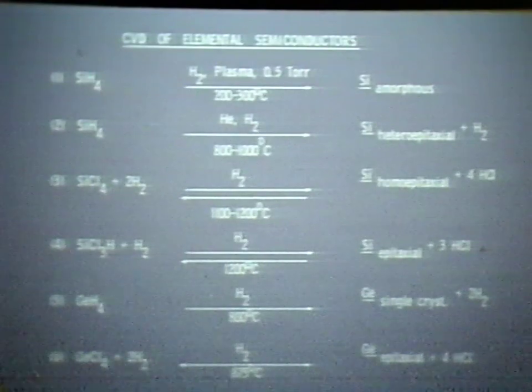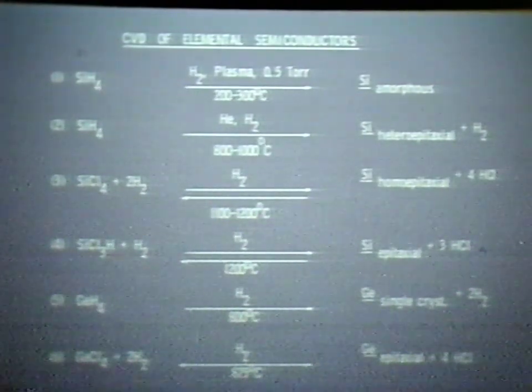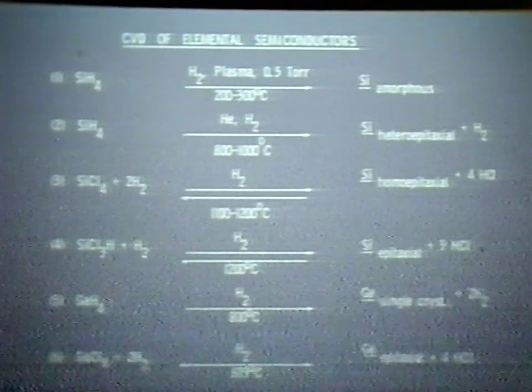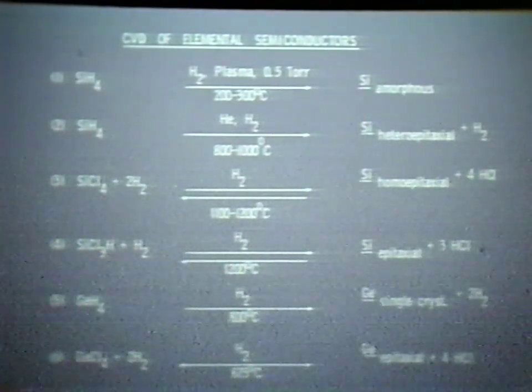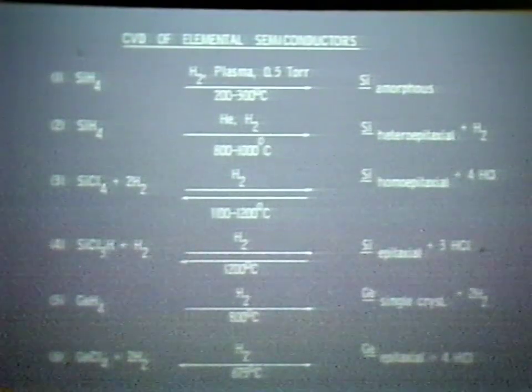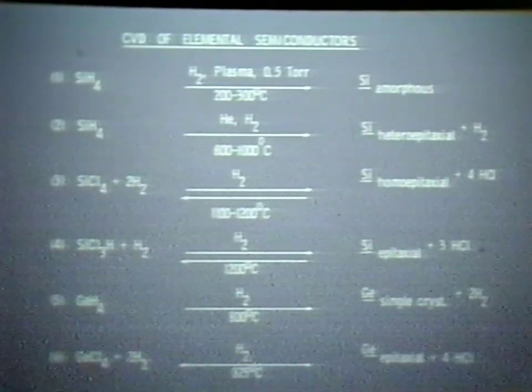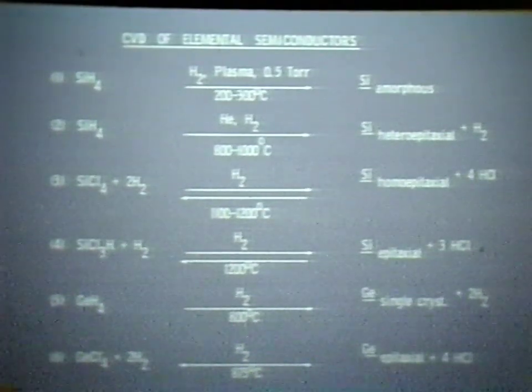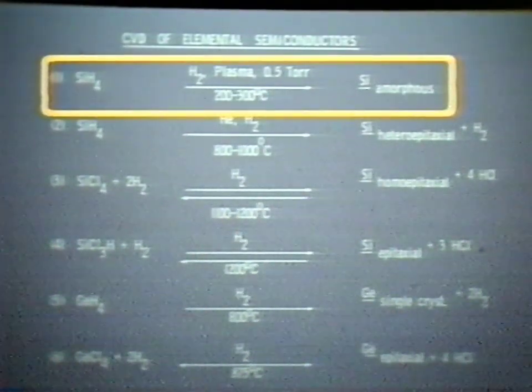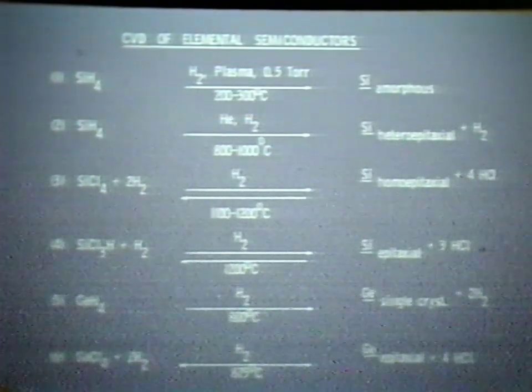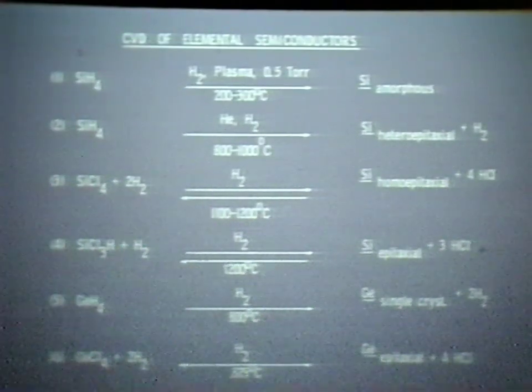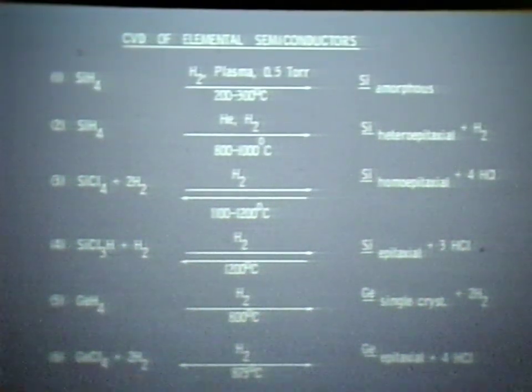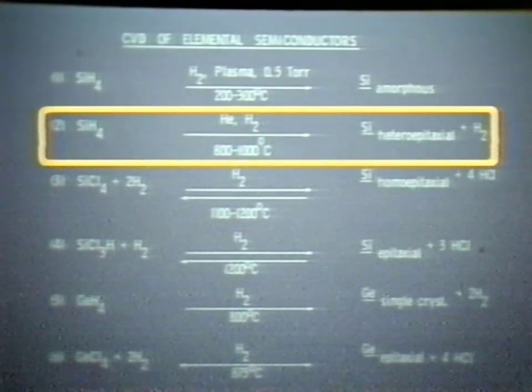So let's have a look at the type of the reactions that can be used for the production of silicon and also germanium. And to begin with here, we have seen that reaction before a few times already. Thermal dissociation of silane in a plasma discharge can produce amorphous silicon at a very low temperature, like 200 to 300 degrees centigrade. Or we can use the reaction listed here, the simple type of dissociation or pyrolysis reaction at 800 to 1000 degrees C to produce heteroepitaxial silicon.